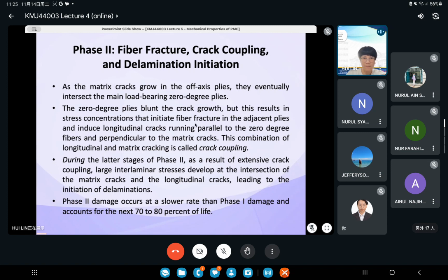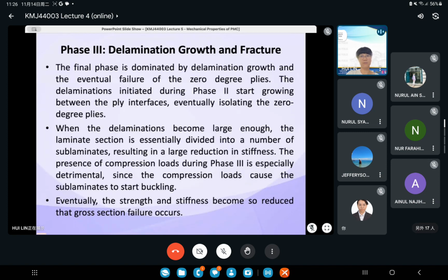Okay, 0 degree fiber perpendicular to the matrix crack. So only then does it go to the fiber. Then the third, it goes to the fiber when the barrier between the fiber and matrix has gone. No barrier already, so the crack will directly extend to the fiber, the carbon fiber. Then the carbon fiber totally fails. Then, of course, delamination grows, and then the whole composite will totally break into two.